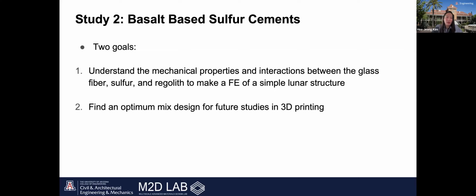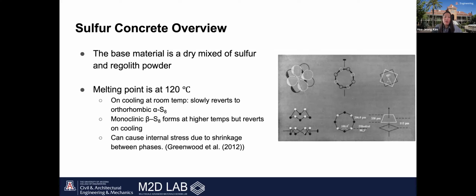And in this study, we used basalt as a regolith simulant since it provides a cost-effective alternative to high-fidelity simulants like KLS-1. And here is some background on sulfur cements. The basic idea is that elemental sulfur is mixed with the dry regolith and then heated to about 120 degrees Celsius. And when the sulfur melts, the mixture becomes a thick, viscous paste that can be compacted or extruded into shape. And as the material cools, the sulfur solidifies and transforms from the liquid phase into the monoclinic beta phase, as shown in the right figure.